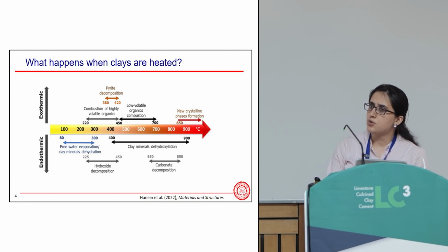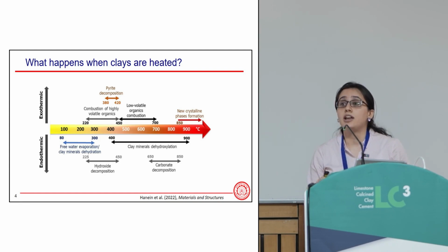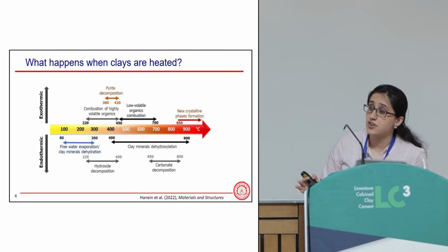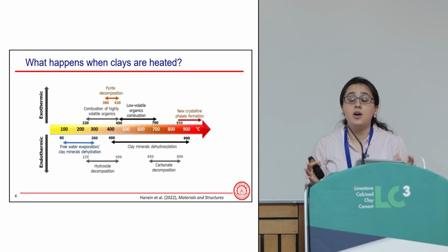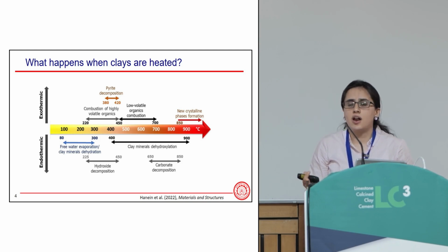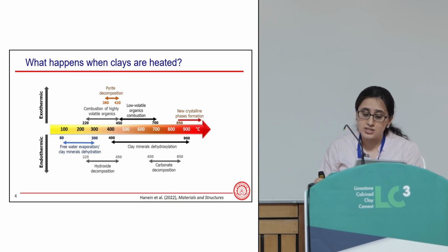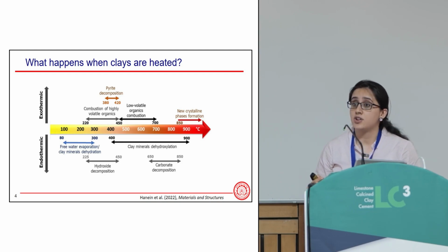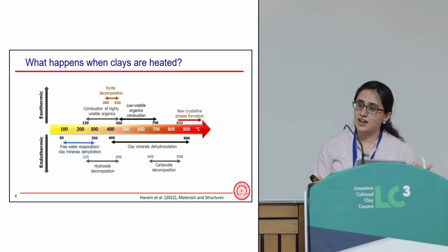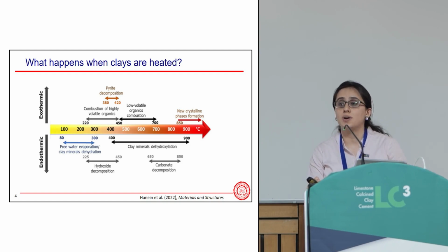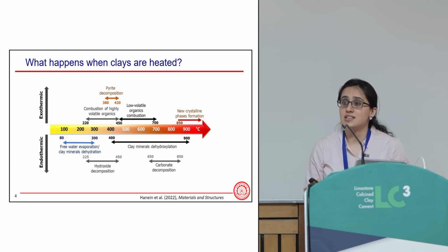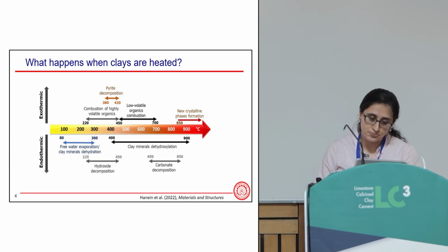So just from the dehydration process, we can get a rough idea of what type of clay mineral is present. Because kaolinitic clays show very little dehydration, like the mass loss in a very high-grade kaolinitic clay will be just around 1 to 2%. While for the smectite clays, these clays show a very pronounced dehydration. So it's a rough indication whether our clays are 1 to 1 or 2 to 1 type of clay. And that is what Rafi also pointed out. That's the reason we dry the sample at 100 degrees centigrade, so that we can see this dehydration phenomenon.